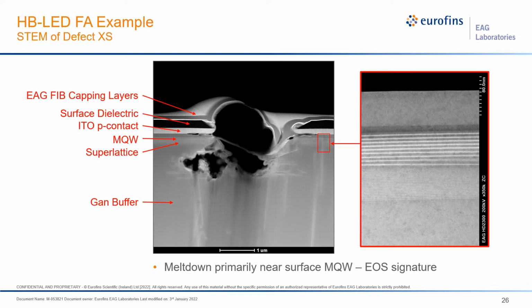And then we can really look at and see the extent of how this defect is formed within the device. If we look at a region here, this is a STEM Z-contrast image, so a high angle annular dark field image, which shows us really nicely the different compositions of layers in the structure itself. You've got the InGaN multi-quantum well region here, and then you've got an InGaN superlattice, some AlGaN electron blocking layer, and your p-GaN cap up here. And then there are some other layers as well, like your surface dielectric and the ITO p-contact over here.